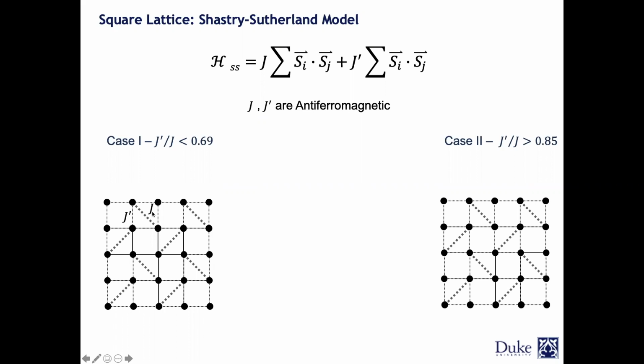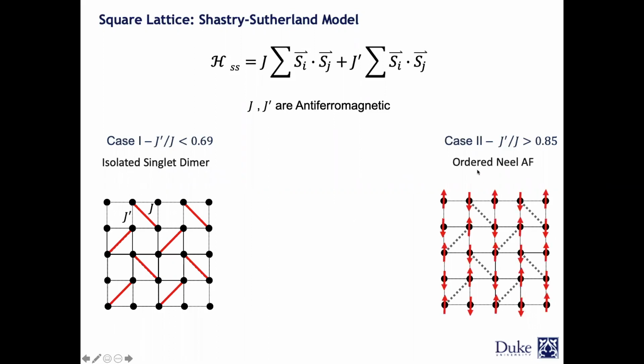You have these competing interactions, and both of them are antiferromagnetic. There are two cases. So one case is going to be J prime over J smaller than a value. The other case is J prime over J more than a particular value. So in that case, if you're in this range, then the ground state, which can actually be solved exactly, is a non-magnetic singlet ground state. And in this case, it is going to be an ordered Néel antiferromagnetic state.